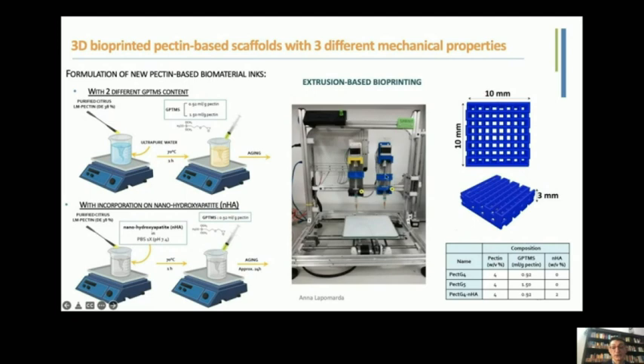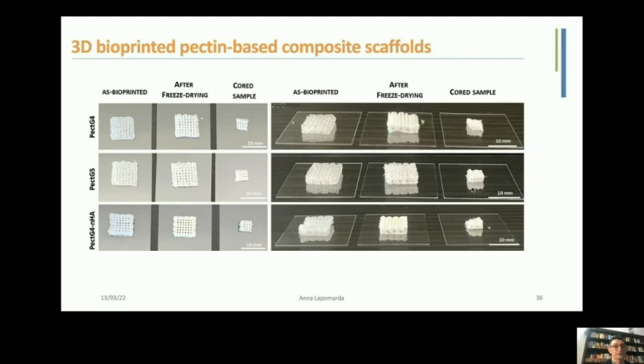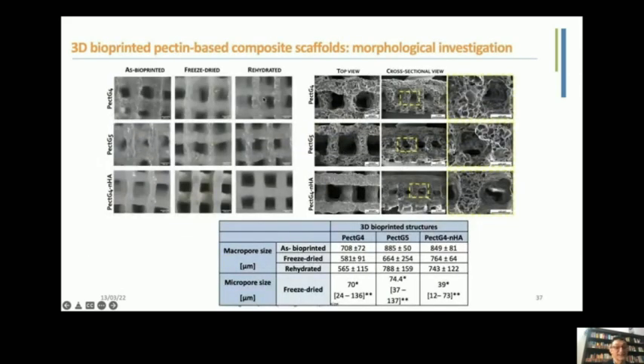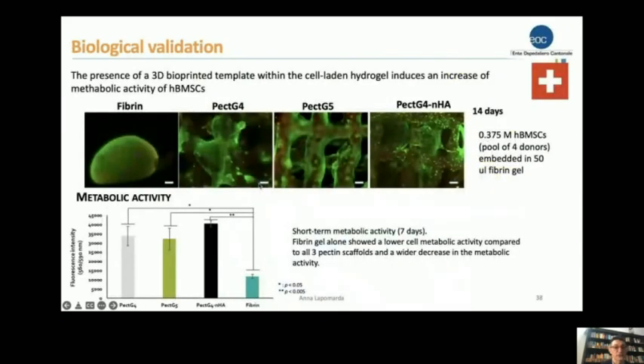And as you can see, with this extrusion system that we developed in our lab, we created a 3D scaffold with a well-defined topology. And here you can see the scaffold that we obtained as soon as we finished printing, after the freeze drying, and also after we stored the samples. So there is a reduction with time. But when we rehydrated the scaffold, we can see that the topology and the features remain. So we preserve the micro and nano porosity.